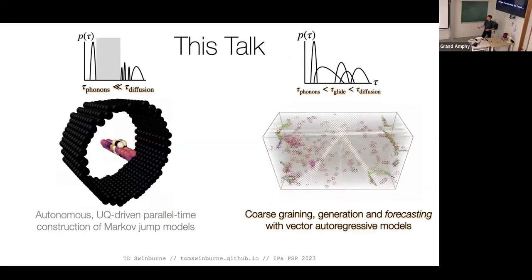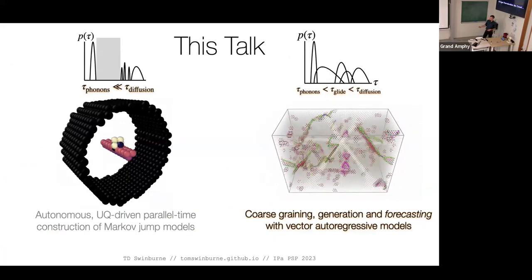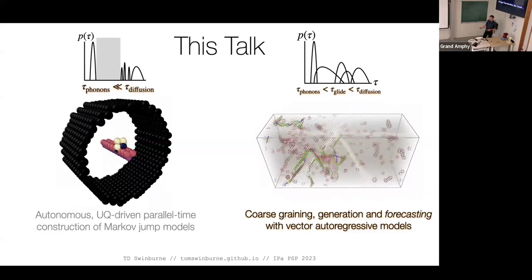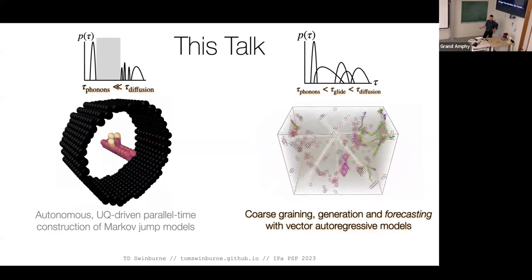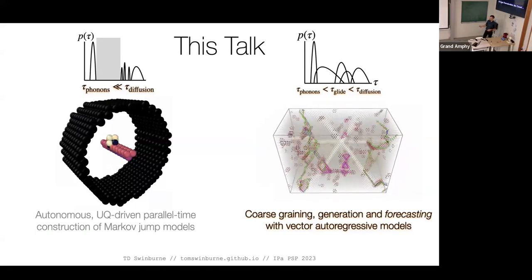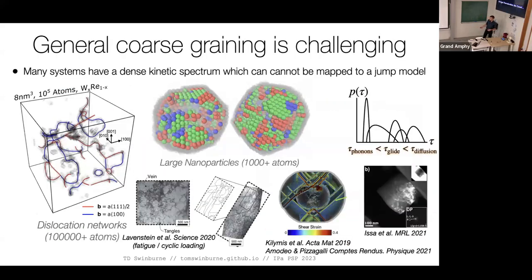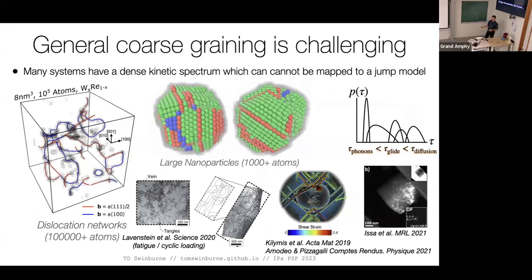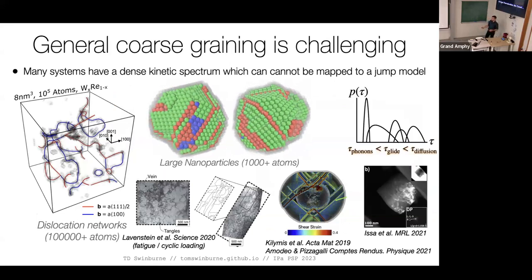This is what we can do if we have a Markov jump model with nice metastability kinetics. But there are lots of cases where this nice metastability, this spectral gap, doesn't really exist. There we have a much weaker theoretical handhold on characterizing the dynamics. For large systems, there's always something happening — no real metastability. Looking at dislocation systems, there's constant viscous aging, non-stationary kinetics, microstructure always changing, and it's not clear how to map this to a metastable type problem.